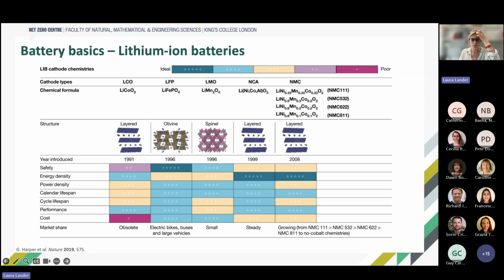So for example, lithium cobalt oxides, which we often use in our cell phones, or other layered materials such as NCA, which was used in previous Tesla models, and NMC materials, which are used practically in all other electric vehicles, are relatively unsafe in that sense, whereas lithium iron phosphate has a very high safety performance. This is also one of the reasons why lithium iron phosphate is coming more and more into the market. Similarly with cost, layered materials such as NCA and NMCs are very cost intense, whereas lithium iron phosphate is relatively cheap. And in terms of cycle lifespan, LFP is much better than, for instance, NMCs, which we are using in BMWs and Volkswagen electric vehicles.